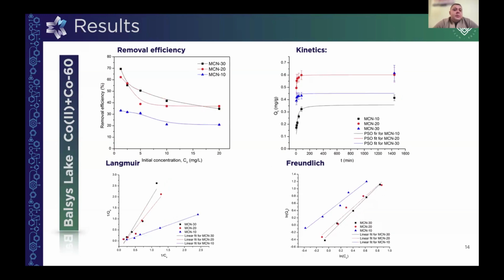And also in Balsys Lake, here we have the best results for removal efficiency. For MCN 30 it's 70%, for MCN 20 it's about 63%, and MCN 10 showed a 33% removal efficiency. Kinetics are similar, and we also calculated the Langmuir and Freundlich isotherms.